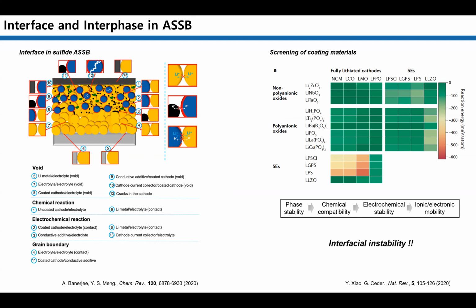For instance, the interface at the integrated cathode tends to form voids due to the solid-solid contact, which increases the internal resistance and affects the stability of the electrolyte contact interface. This issue is critical for our solid-state systems, especially because an intercalation-based cathode is used and any slight volume changes can create a void.